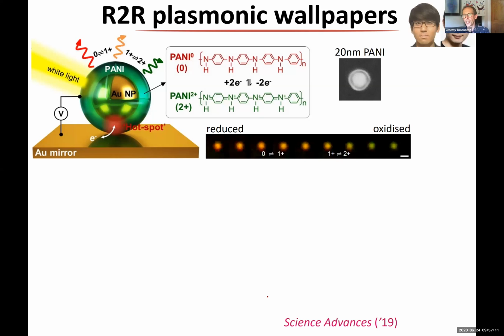So just to end up, I'm going to show you something. We can come back to that, but I'm going to show you one final thing, which is just that you can actually use these for devices. So what we've done here is we've used in the gap, now we've used an electrochromic system. So we've taken the gold nanoparticle and we've coated it with polyaniline, which is an electrochromic polymer, and it can do this redox change between oxidized and reduced, and it changes its refractive index very strongly when we do that. What that does is it changes the color of the light that's trapped in there. And you can just see this by eye as we go between reduced and oxidized states for a single nanoparticle on mirror. So what we can see is that we can go all the way across the spectrum, essentially.